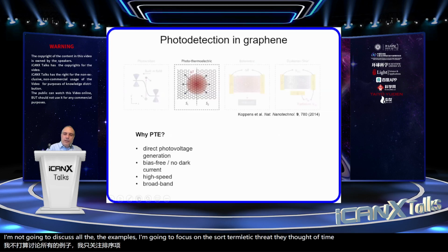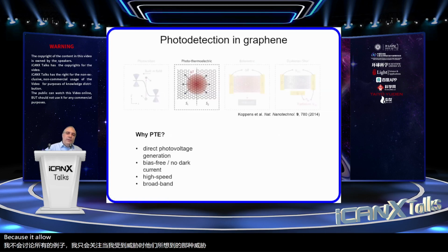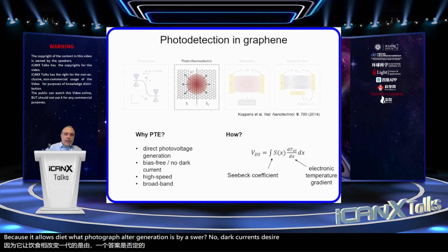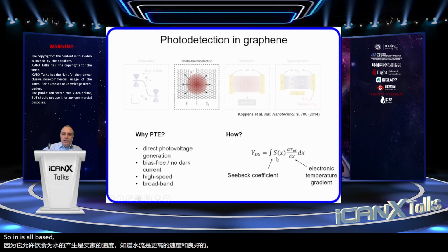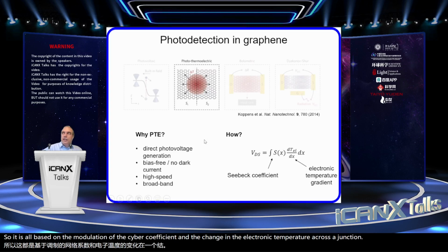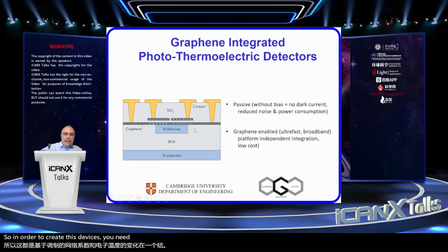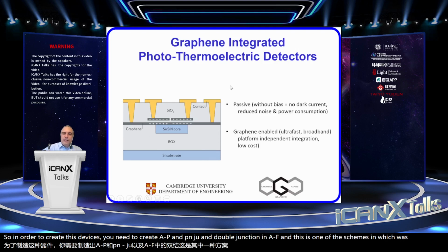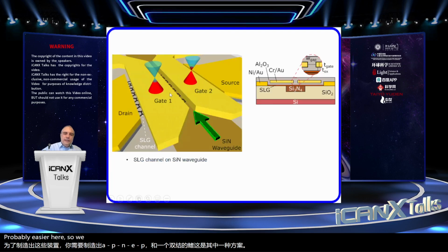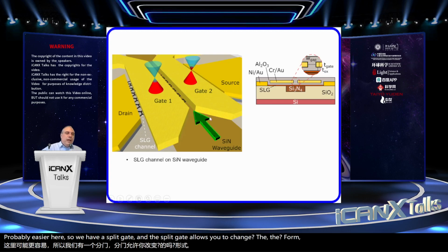The photothermoelectric effect is good because it allows direct photovoltage generation, is bias-free, there are no dark currents, is high speed and broadband. And it is all based on the modulation of the Seebeck coefficient and the change in the electronic temperature across a junction. So in order to create these devices, you need to create a PN junction, a double junction in graphene, and this is one of the schemes in which it was done, probably easier here. So we have a split gate, and the split gate allows you to change from P to N the doping of graphene next to each other, and that creates the modulation of Seebeck coefficient that we need.